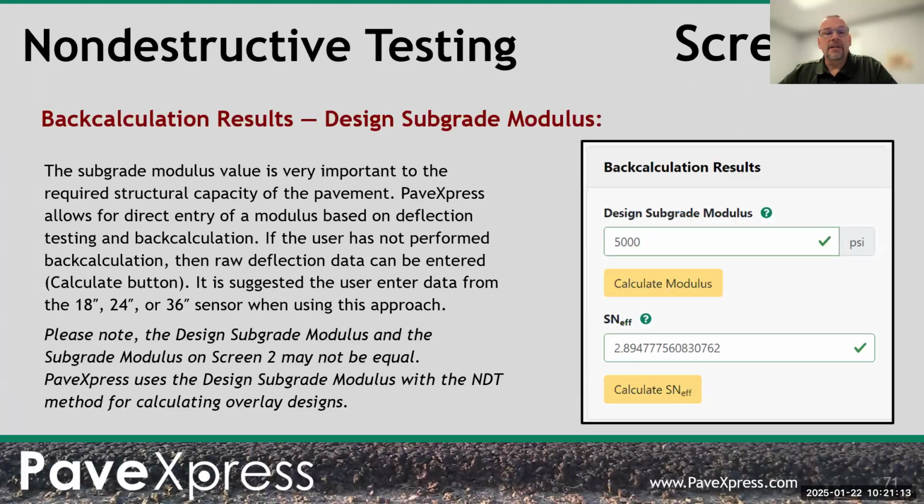If the subgrade modulus comes from a third-party application or software, make sure it's corrected. The correction factor is usually based on the type of subgrade soils. It should be noted this value from Backcalculation may not match the lab obtained value. The lab value may be from 1 or 2 soil samples. Backcalculation value usually comes from numerous test points and is either averaged or using a percentile value.